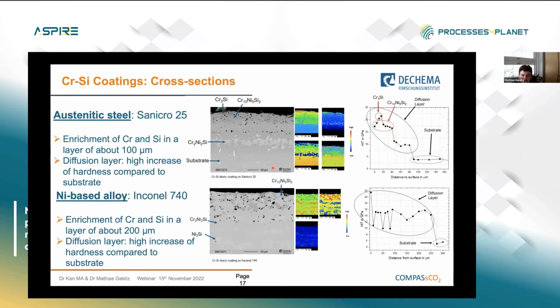The same is true below for an Inconel 740 alloy. Here you can see that we have much more nickel in our outer coating, due to the fact that we have a nickel-based alloy here. Also, we have to add a little bit of nickel to our slurry. So we form not only the A15 phase, we also form a chromium nickel silicon intermetallic phase, but still we achieve this goal of a hard outer layer without cracks.